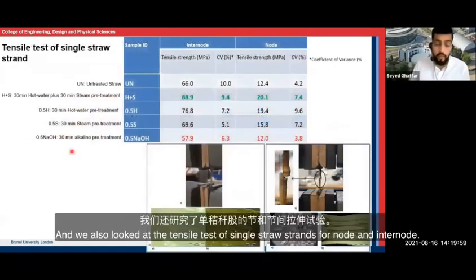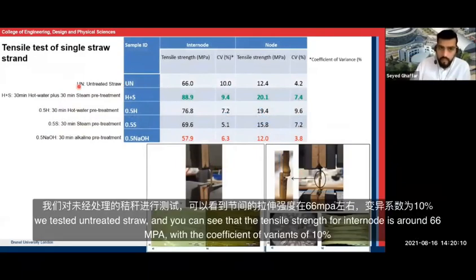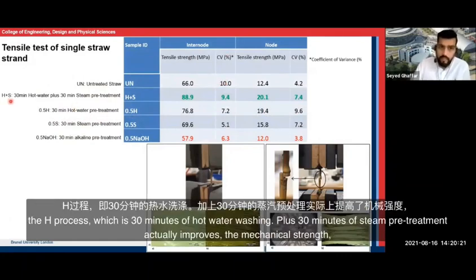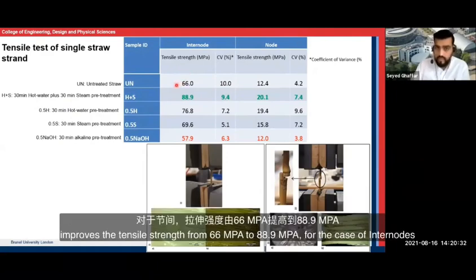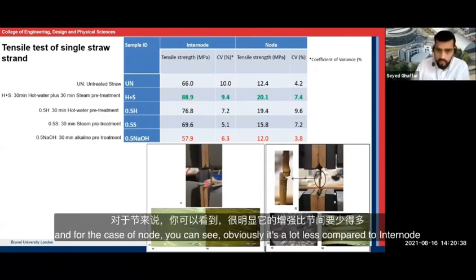And we also looked at the tensile test of single straw strands for node and internode. We tested untreated straw, and you can see that the tensile strength for internode is around 66 MPa with a coefficient of variance of 10%. The H plus S, which is 30 minutes of hot water washing plus 30 minutes of a steam pretreatment, actually improves the mechanical strength, improves the tensile strength. So from 66 MPa to 88.9 MPa for the case of internode. So these are the internodes.